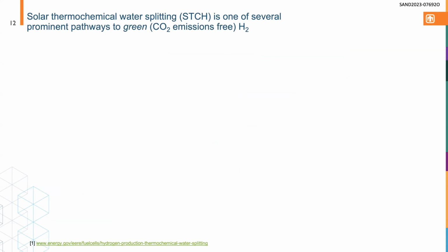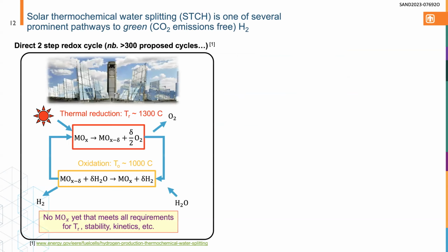So STCH is one of several prominent pathways to create green hydrogen, or CO2 emissions-free hydrogen. I briefly alluded to this, but the way it works is that you have a really high temperature solar receiver. That's actually a picture of the solar tower at Sandia. It's not one of a kind, but not the usual thing that most people have access to. You go to really high temperatures to reduce the metal oxide and liberate oxygen from the lattice, and then you expose it to steam, still at high temperatures, and you then produce hydrogen.